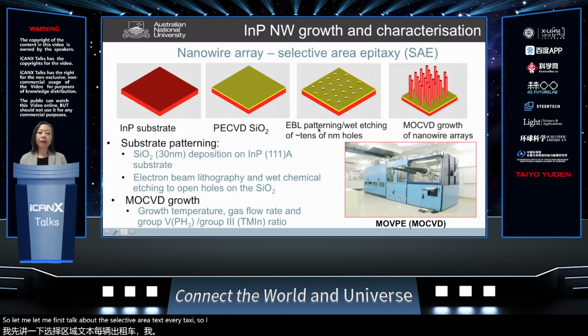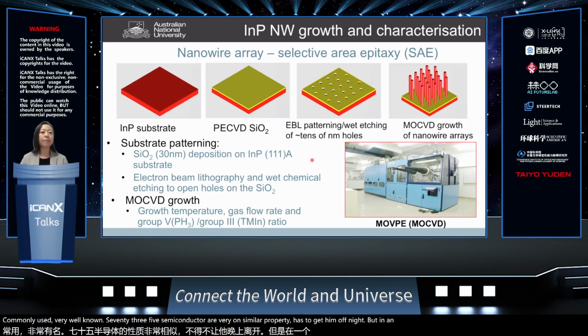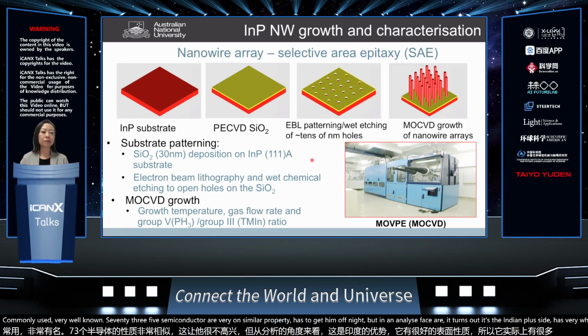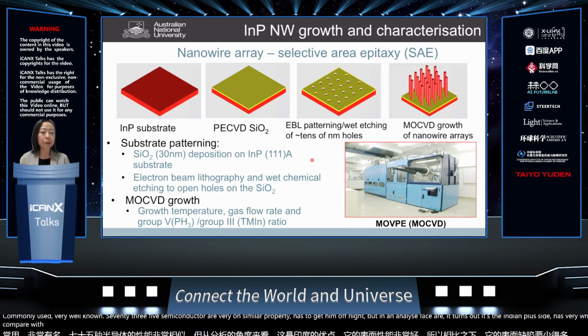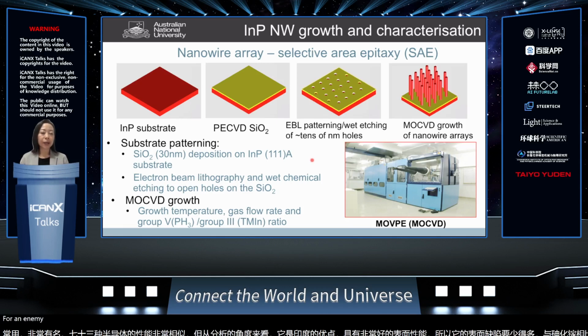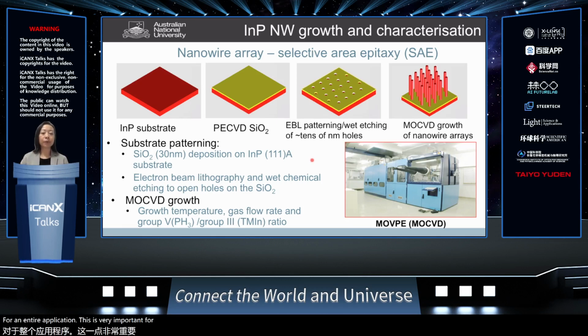So the system I'm going to mainly talk about today is indium phosphide, which is a very commonly used, very well-known III-V semiconductor, and has very similar properties to gallium arsenide, but in the nanowire space, it turns out that indium phosphide has very good surface properties. So it has actually much fewer surface defects compared with gallium arsenide. So for nanowire applications, this is very important. So that's why we selected this material system to do a lot of work.